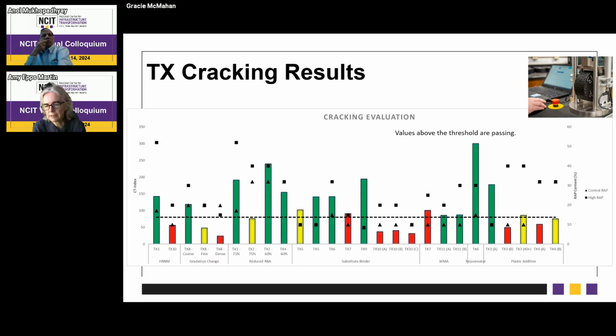So this is a lot, but just to complete the presentation, I just want to indicate that we are doing an analysis. And what you're seeing with the black dots is going from the triangle up to the square. That's how much of a jump in RAP content. So remember, I told you typically we're below 20%, and we're trying to go above 25%, in some cases all the way up to 50%. And when we do that, though, we don't want to sacrifice our cracking performance. So we want it to be at least as good as a control or a typical RAP content, which would be the yellow bars. So at least as good as the control, or even better than the control, as long as we're applying a strategy, which are the green bars.